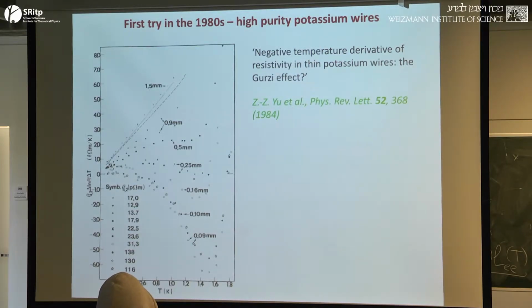So the first try at seeing the Gurzhi effect, and the first claim, that's the title of the paper, was a really interesting thing. In the days when they couldn't microstructure, what they could do was to make very, very pure elemental metals, and they could extrude them and anneal them very carefully to keep them extremely pure as they extruded them. So this paper got down to 90 micron wide potassium wires. And they then studied the resistivity of the potassium wires, plotted it in a rather obscure way, but essentially what they found was that they got a negative thermal derivative of the temperature dependence of the resistivity.